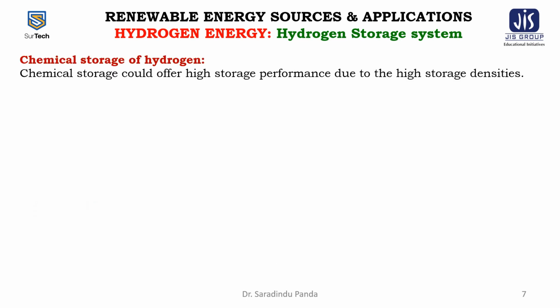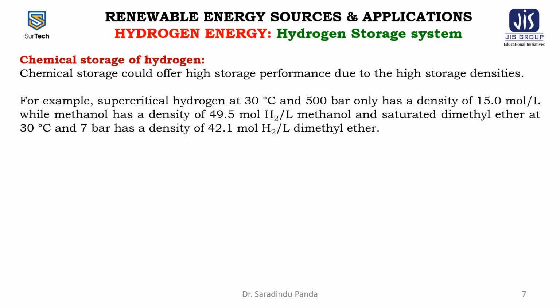Now come to the chemical storage of hydrogen. The chemical storage could offer high storage performance due to the high storage densities. For example, the supercritical hydrogen at 30 degrees centigrade and 500 bar only has a density of 15 mole per liter, while the methanol has a density of 49.5 mole hydrogen per liter methanol, and saturated dimethyl ether at 30 degrees centigrade and 7 bar has a density of 42.1 mole hydrogen per liter dimethyl ether.